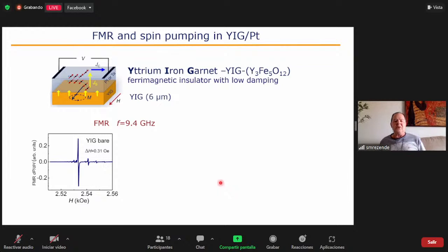YIG is very much used today for making spin pumping experiments. Let's say that we take a YIG film. The YIG film can be made by sputtering, but also by other techniques that produce very good single crystal films. We deposit, for instance, a platinum layer on top of this. We do ferromagnetic resonance. Here is the ferromagnetic resonance response.